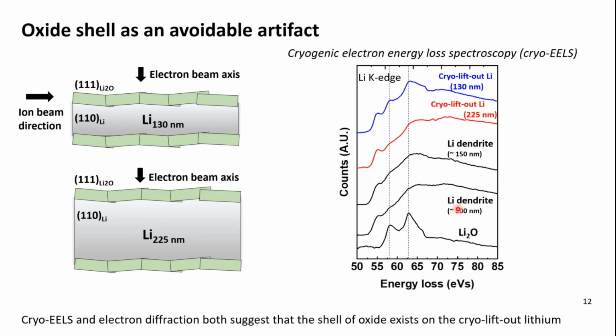The following graphical illustration shows my hypothesis from the diffraction observation in the previous slide. I hypothesized that I have two different ratios between lithium and lithium oxide when the ion beam sweeps through the reactive lithium. When the ion beam sweeps through the lithium, it can create a constant thickness of lithium oxide. And in order to match the diffraction pattern result, I also performed yield analysis, and we found the thin cryo-lift-out has less lithium oxide along the beam axis, as you can see from the blue curve, which represents the thin lamella.